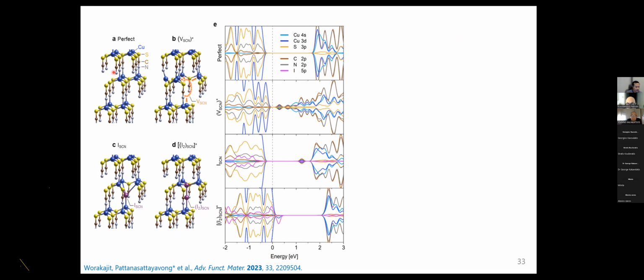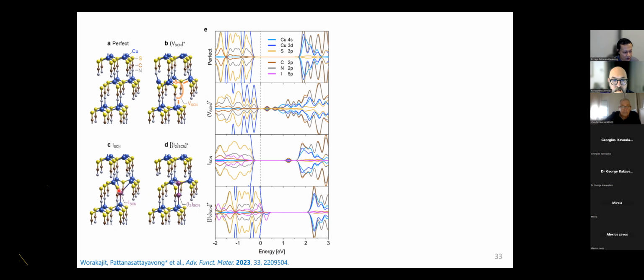So we look at the perfect case compared to the thiocyanate vacancy case, and we can see that it becomes messy, basically a lot of defect states here, especially the donor states. Because copper thiocyanate is p-type, we don't like donor states, because donors would either produce electrons that would neutralize the holes, or they could become hole killers. And then we also prove from the theory that when we substitute the vacancy here with iodine, it can reduce the number of the defect states.